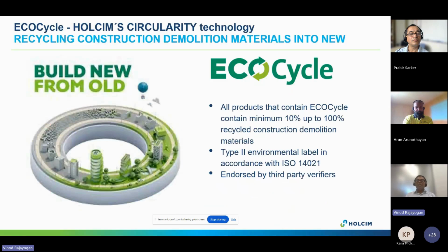With that, we have got a brand, EcoCycle. EcoCycle for us is any product within the concrete that has a minimum of 10% recycled content. To put it simply, concrete has 2,400 kilos per cubic meter, and we are talking about a minimum of 240 or 250 kilos of material being recycled. That will equate to at least 30% of coarse aggregate if we were talking in terms of recycled concrete aggregates. We also wanted to go a step further and say that we will not claim EcoCycle until it is third-party verified. And this is a process we are currently going through as part of this journey.